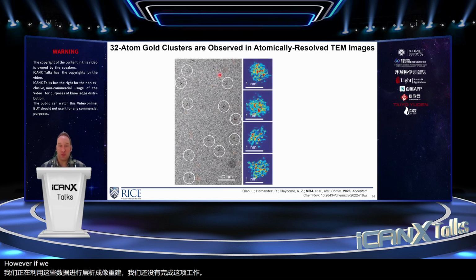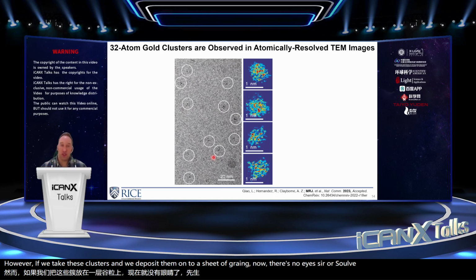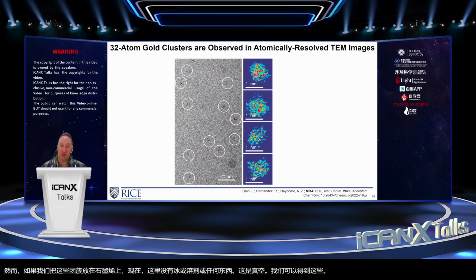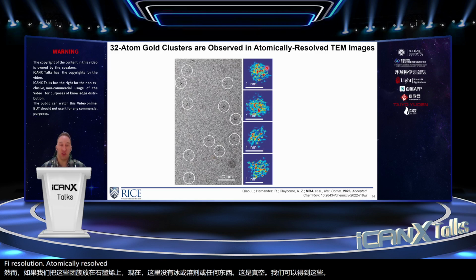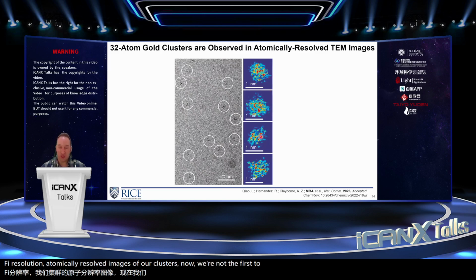However, if we take these clusters and deposit them onto a sheet of graphene, now there's no ice or solvent or anything present here. This is in vacuum, and we can get these really nice high resolution, atomically resolved images of our clusters. Now, we're not the first to attempt to image clusters with TEM.